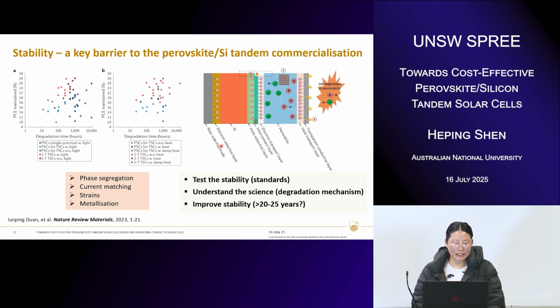In one of our previous review and perspective papers, we summarized the stability of the perovskite silicon tandem versus the single junction. We found that actually the tandem stability is even more challenging compared to the single junction. If we look at the measurement time, the red dots on this curve are the tandem, and the blue is the single junction.